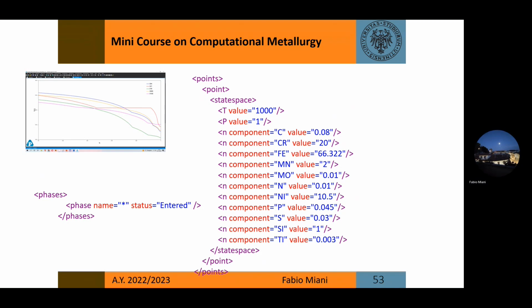It is important to state that for this specific software, the sum of the chemical elements should be up to 100. So when you read zero, sometimes you should propose a possible value close to zero, but not totally zero. For instance, in steel, more than 30 ppm of titanium is normally not that much.